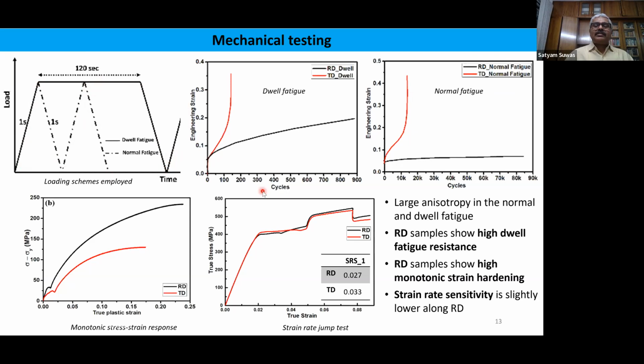And then the strain versus cycle plot very clearly said what was at least anticipated from indirect responses about anisotropy: the material which was extracted along the transverse direction had shown dwell fatigue sensitivity in this manner, right? So this has accumulated a very high amount of strain in a very short number of cycles. And for the one along the rolling direction, we could see that the strain accumulation versus number of cycles follows this trend. Under normal fatigue also, this was similar. Only thing is the degree was a little higher in the case of dwell fatigue compared to normal fatigue conditions.